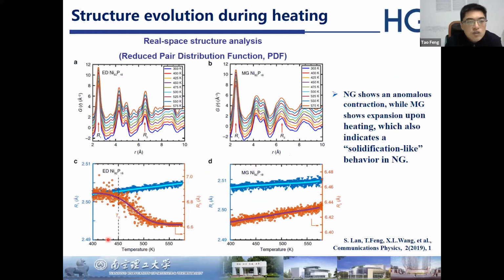And we can also get similar information from the reduced pair distribution functions. The nanoglass shows an anomalous contraction. What does this mean? This red one is the third peak position upon heating, and it just shifts to the short distance. That means the contraction upon heating, while the metallic glass just shows thermal expansion upon heating. So this also indicates there is a solidification-like behavior in the nanoglass.